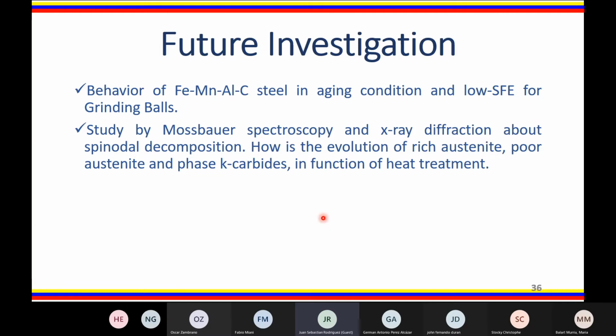In the future investigation that we have to develop, according to the previous results, are the following: study the behavior of FeMnAlC steel in aging condition and low stacking fault energy condition for grinding balls, and a study by Mossbauer spectroscopy and X-ray diffraction about spinodal decomposition. How is the evolution of rich austenite, poor austenite, and phase carbide as a function of heat treatment? Finally, in all this time of work, many new questions continue to arise as we find interesting results, which deeply awaken our interest to continue working on these types of steels.